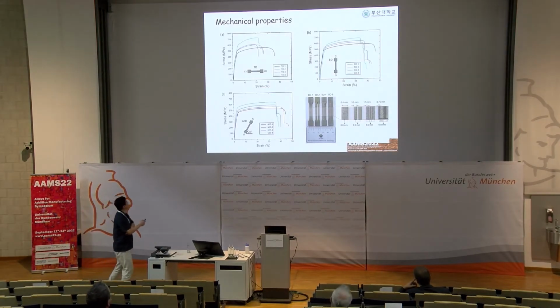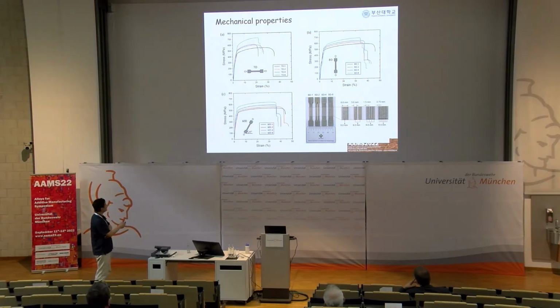So looking at the mechanical properties of those specially designed samples, the size effect was really pronounced in the horizontal direction. As we can see here, the black line is sample number 1, which is the normal shape. And when we increase the area of the laser contour scanning, we are basically increasing the yield strength and decreasing the elongation. This effect was the most pronounced in this direction, but there are effects with the same trend in the other directions as well.